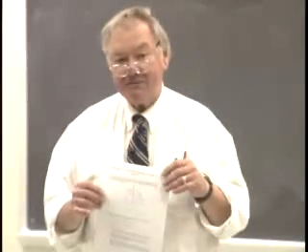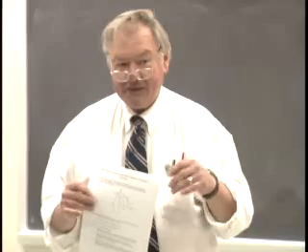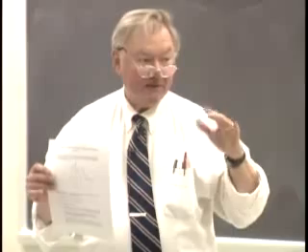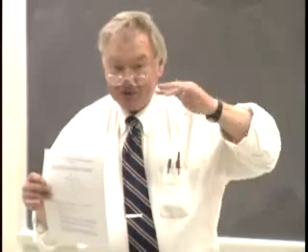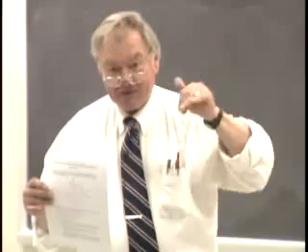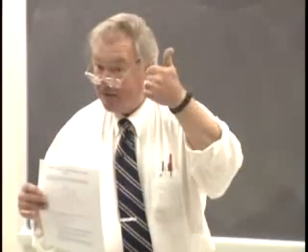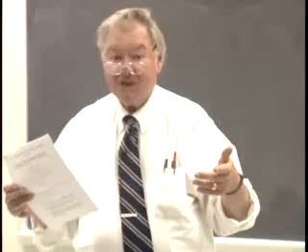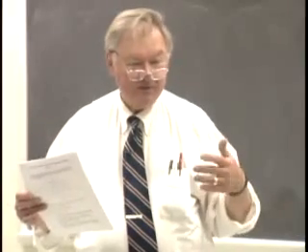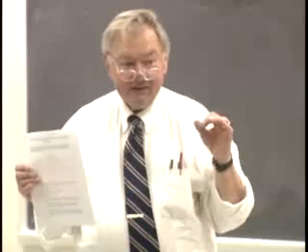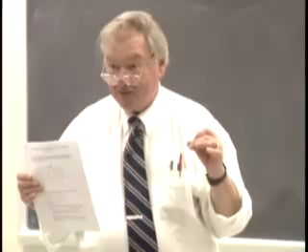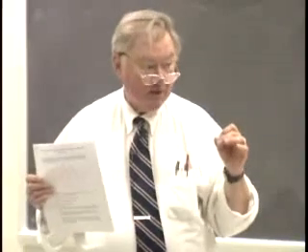And the interesting thing is you could measure these angles very precisely with a device called a reflecting goniometer. Provided you had a crystal with nice shiny faces on it, you had a two-circle instrument and you could adjust the crystal so that a light beam, a very finely collimated beam of light, was focused into an eyepiece. And you could measure angles to within not 1 minute, but 1 second of arc. And from this, if you could assign Miller indices to the faces, you could deduce not the absolute magnitudes of translations, but the ratio of them.